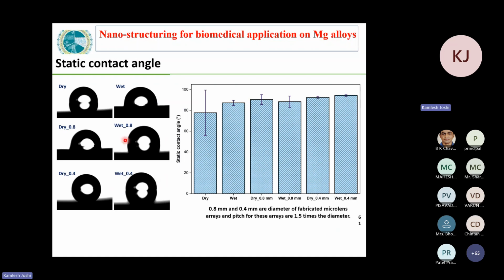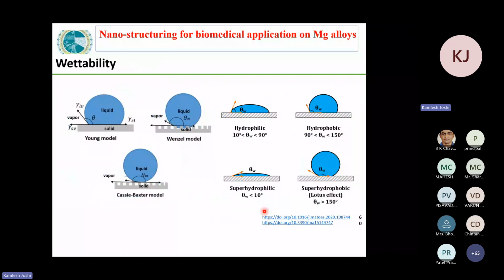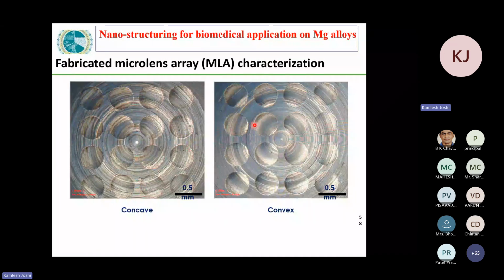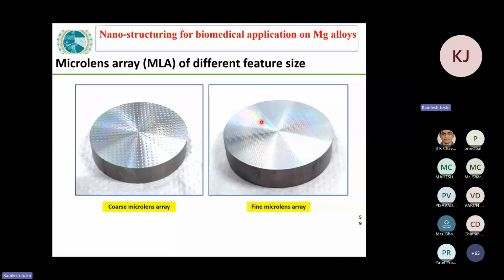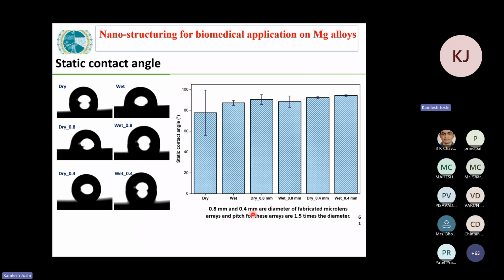So these are some of the results which we got, and these are for the 0.8 mm and 0.4 mm diameter micro arrays. So you can see these diameters. The diameters are 0.8 and 0.4 mm micro. The pitch of these arrays were 1.5 times the diameter. The conditions used were the dry condition as well as the wet condition.